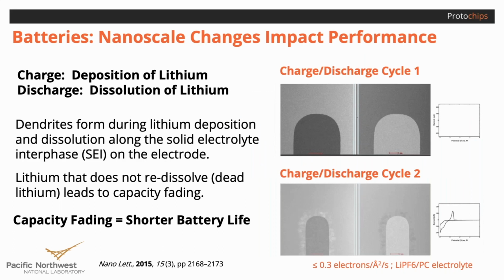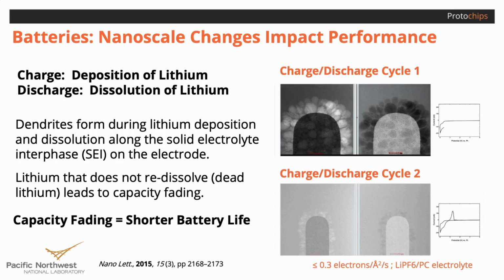In this example, researchers from the Nigel Browning and Leila Mehdi group studied the charging and discharging process using lithium hexafluorophosphate. In this experiment, they are using a platinum electrode whose surface is clearly visible. During the first charging cycle, as the potential is swept in the negative direction during the charging process, lithium electrodeposition occurs, resulting in a buildup of lithium dendrites on the surface of the electrode. These dendrites do not fully redissolve upon discharge as the potential is swept in the positive direction back into the electrolyte.